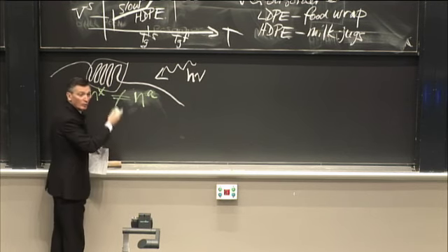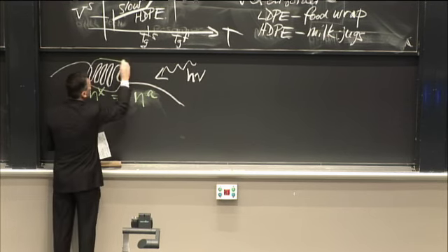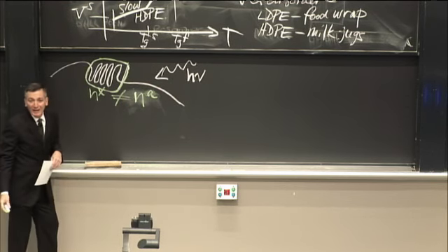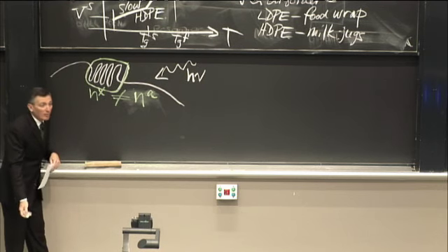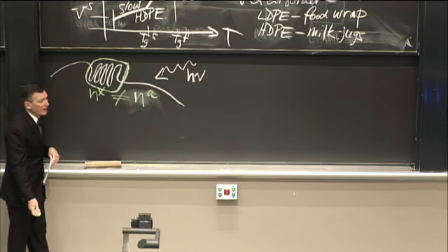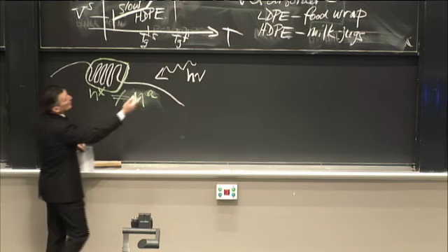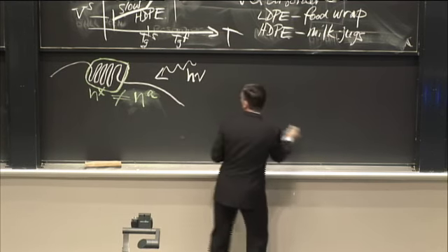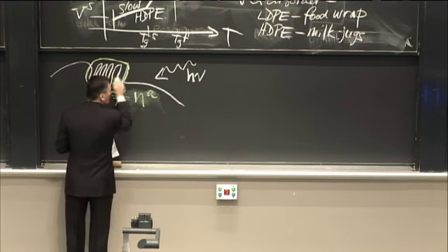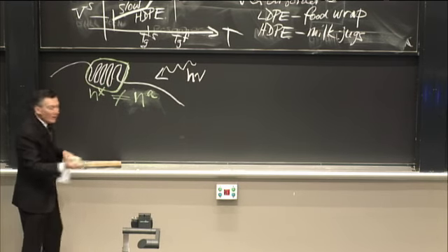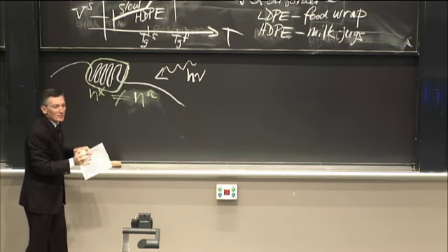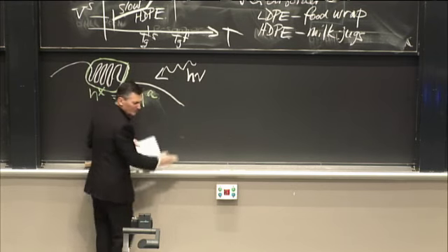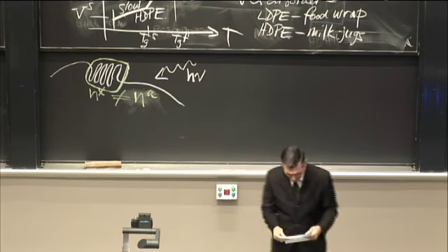Even though each zone is clear and colorless, can you see that this boundary between the ordered and the disordered zone acts like an interface? And what happens when you have an interface with a different index of refraction? It scatters light. And as a result, the milk jugs, they appear white. You can't see through them even though they're constituted of the same continuous material, but there's these density fluctuations because this is higher density than this. So you can rationalize all of this stuff.